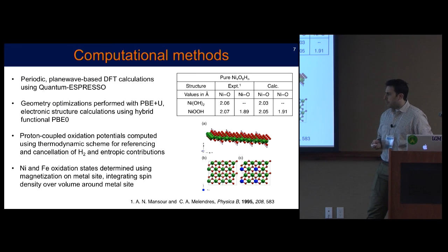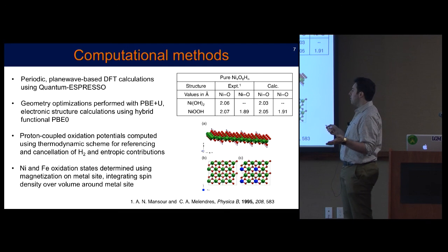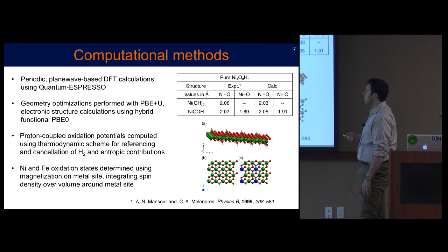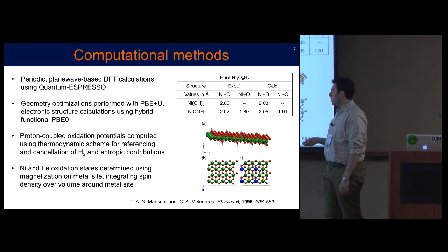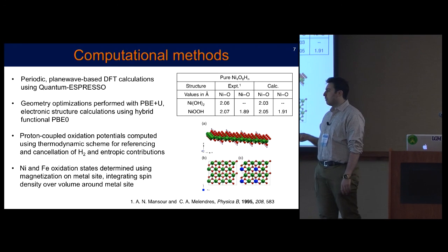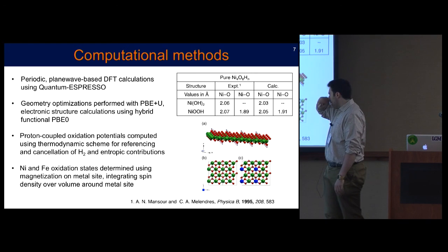Okay, so briefly on the methodologies, at least computational methodologies, we did a periodic boundary condition, plane wave-based DFT calculation using the open source Quantum Espresso suite. And we optimized the geometries for this material at a DFT plus U, or GGA plus U, level of theory, which gave us good bond lengths in comparison to X-ray experiments.